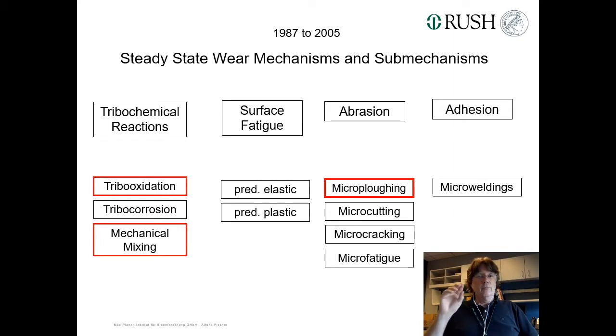But the big wear particles destroy your contact situation, and then your contacts are limited to a very limited number of mobile asperities. This is how I look at wear particles, while these nanoparticles can act like a lubricant.